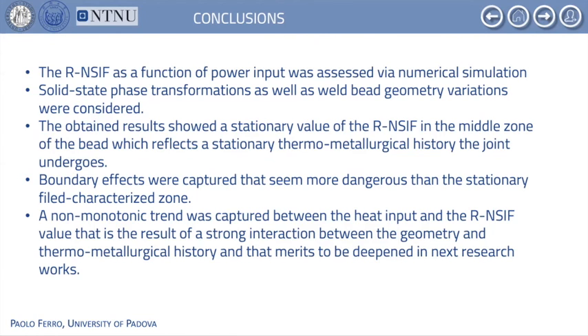Finally, a non-monotonic trend was captured between the heat input and the residual notch stress intensity factor value, which is the result of a strong interaction between the geometry and the thermometallurgical history, and that merits to be further investigated in the next research work.